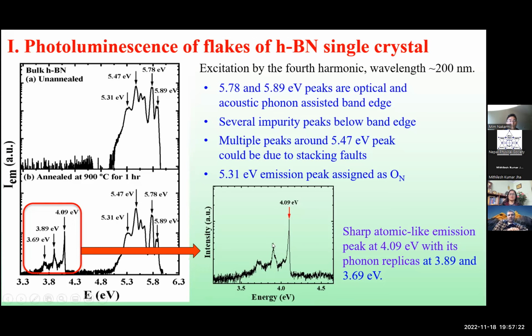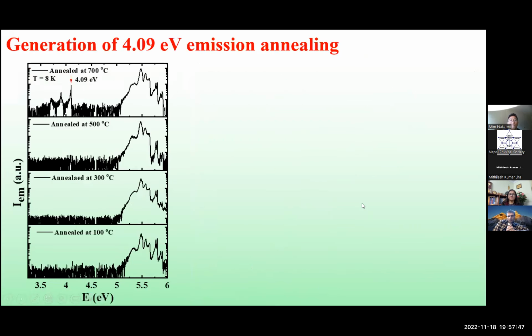Additionally, there are two other peaks, 3.89 and 3.69 eV, with a 0.2 eV difference. That 0.2 eV is actually the phonon energy in boron nitride. So these are the phonon replicas, and the zero phonon line, the main peak, is the 4.09. After that, we tried to figure out how to generate this